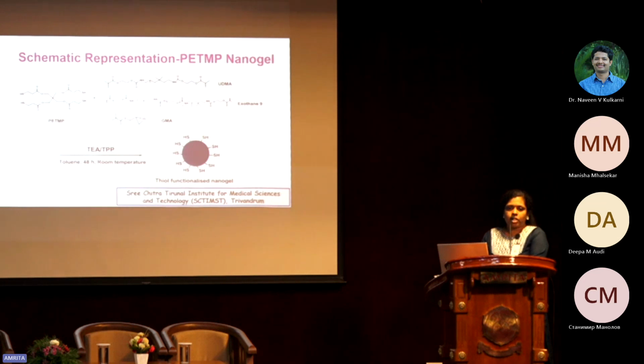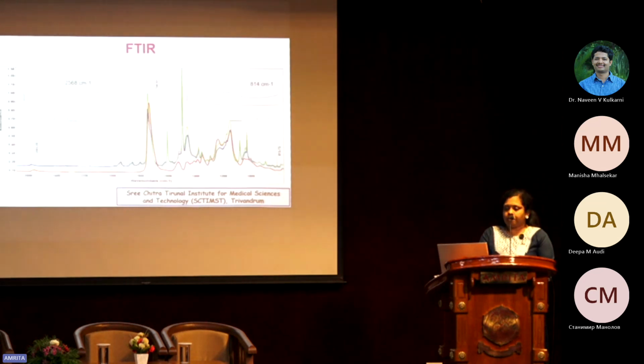also thiol functionalized. So in Michael addition, it's like a step growth reaction. So it's like a 1:1 reaction of acrylic and thiol. So if we are choosing the feed ratio in such a way that the thiol is in excess quantity, we can get thiol functionalized nanogel, or in the other way, if we are taking the feed ratio in such a way that the acrylic groups are more in the reaction mixture, then we can introduce the acrylic functionality in the polymer system. So here we introduce the thiol functionality by taking the excess of PETMP in the system.